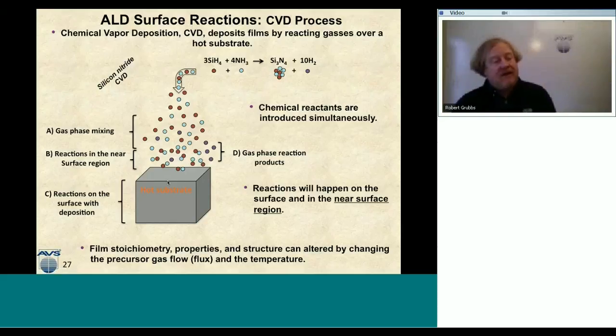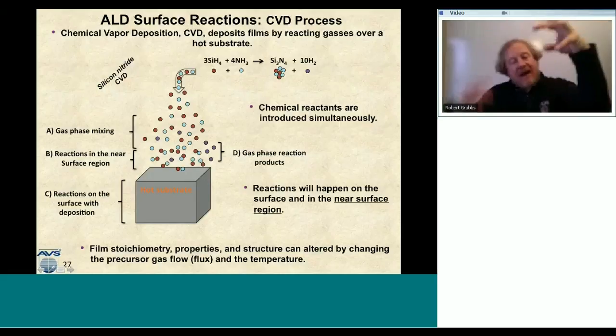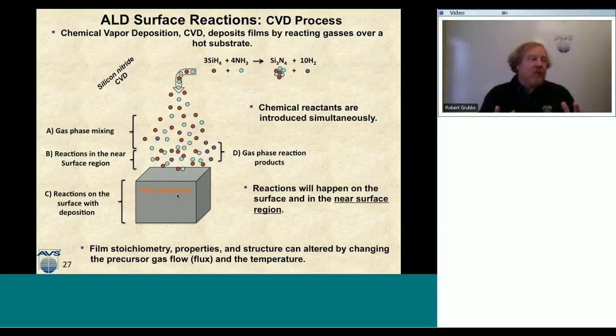One thing to note about a CVD reaction is that there are really two different kinetic regimes. When the substrate is so hot that everything that comes down onto the surface will react and form a film, then we're in the mass transport limited regime. The temperature is so hot, it doesn't matter how hot it is, and the number of molecules that come to the surface actually react on the surface, and the film thickness grows at a rate determined by how much I bring in, the flows or the flux of the chemicals. The second regime in CVD is the kinetic regime, at a lower temperature, where I have a bunch of these gas phase molecules near the surface, and they're constantly being pumped out. But the kinetics of the reaction determine the growth of the film. So those are two different regimes in the CVD process.